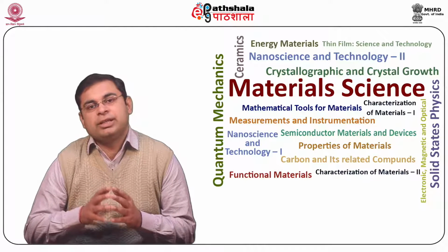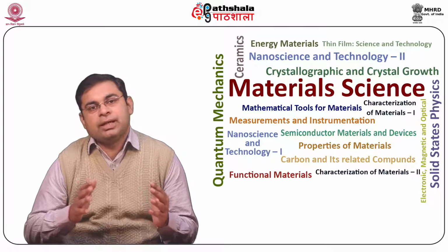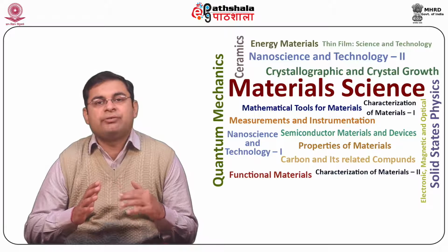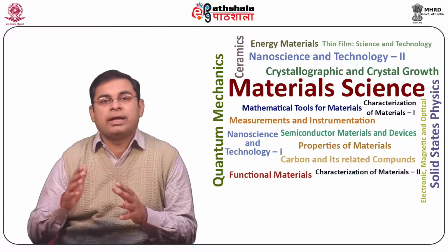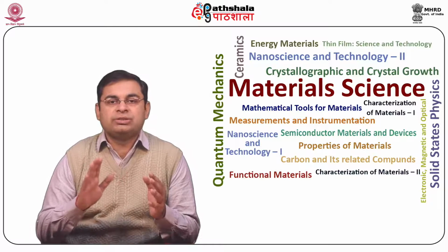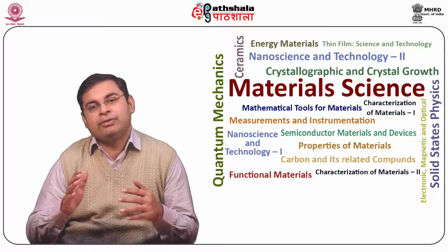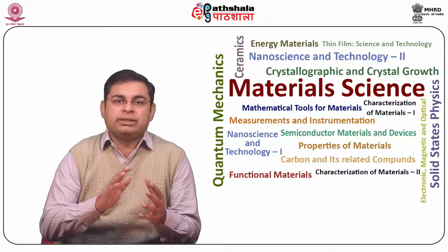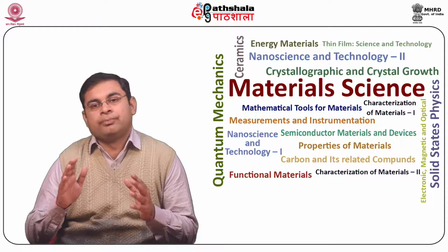The type of conduction is strongly affected by the shape of the energy surface, that is, the band structure. The electronic states which have energies near the bottom of the band, or the lowest lying allowed states, act as free electrons, with the exception that they respond to the applied field like lighter or heavier particles. Thus, the mass of the electron m changes to the effective mass m star.